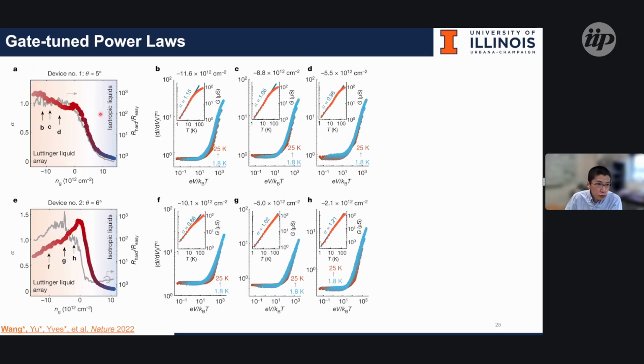If we push further and tune the density, we can suppose the displacement field is zero, and then see the power law behavior as well as the anisotropy. The gray line as background is the anisotropy of the system, and the transition of the dots from red to blue represents the numbers we extract for the power law of the system.